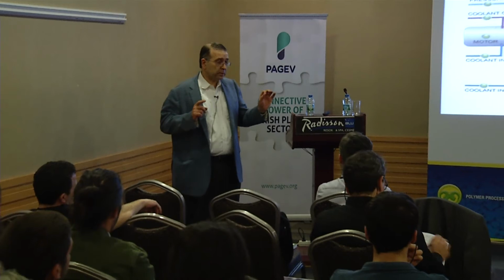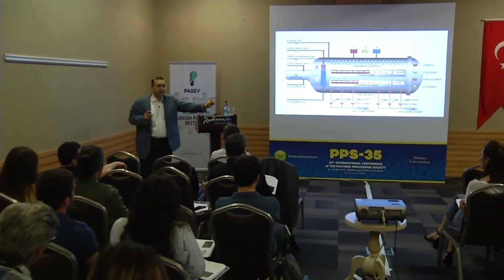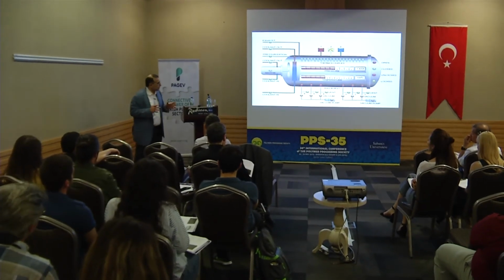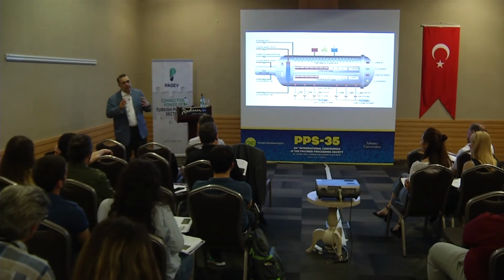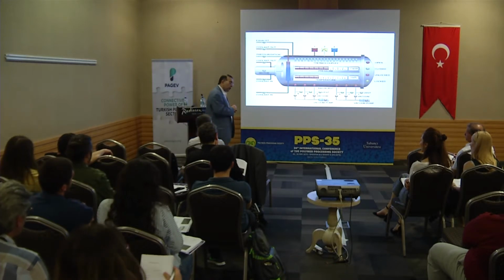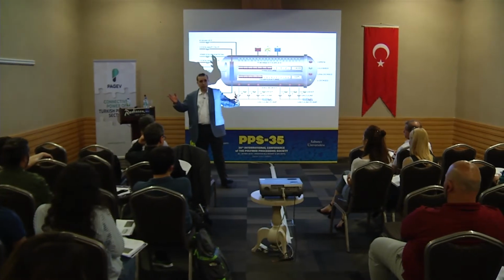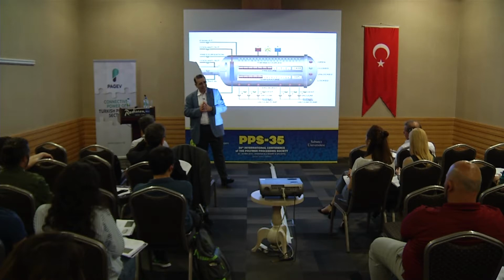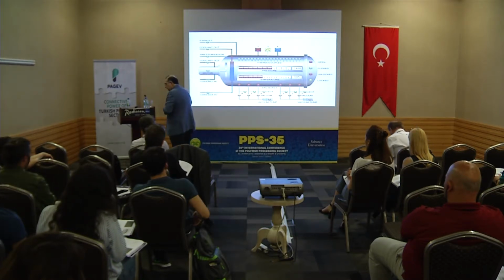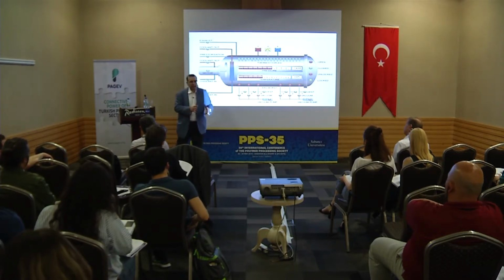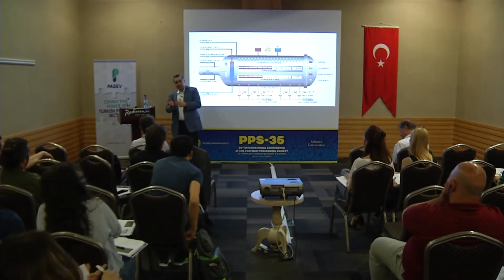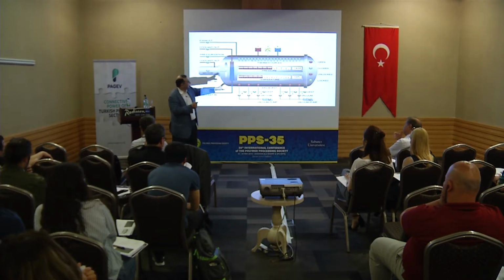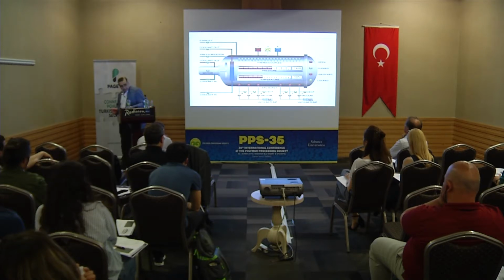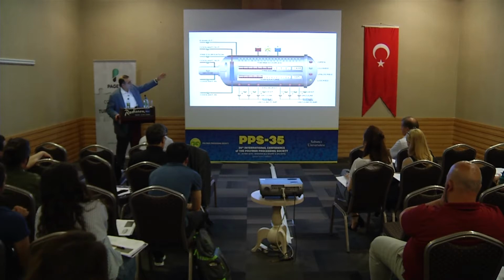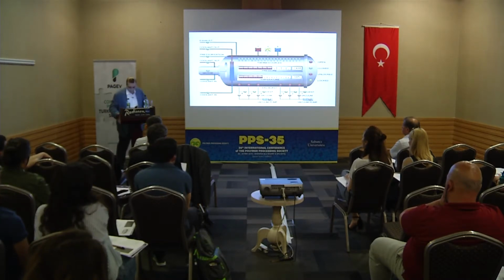So it is always a good practice to have multiple thermocouples, and one thermocouple will give you the autoclave temperature, so that follows the cure cycle, okay? And then other thermocouples will be on the part or next to the part, so you will have a group of thermocouples that gives you the temperature of different parts of the autoclave. And although you would like to have a uniform temperature, it really is not uniform. There might be a 5-10 degree variation within the autoclave. So depending on where you put your part, you may not follow. There will be some leading thermocouples, some lagging thermocouples, right? So you have to have some sort of software to tell you, depending on the thermocouple, heat it up, don't heat it up. Heat it up, don't heat it up.